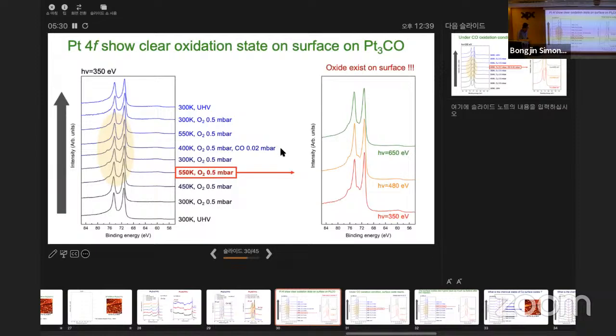So what we did was, at 0.5 mbar of oxygen with a temperature of about 550 K, that's the cobalt oxide, we did the energy scan so we know where this oxygen is coming from. This 350 is more surface sensitive, 650 is more bulk sensitive, and you can see that more features can be seen at surface sensitive energies. So this one is on the surface, that one for sure. So we identify at least that oxide exists on the surface.